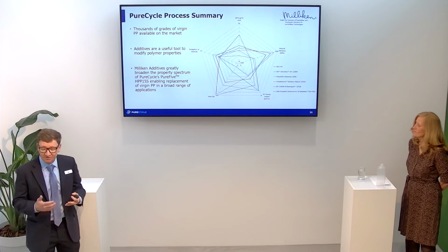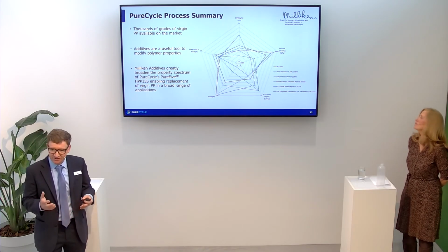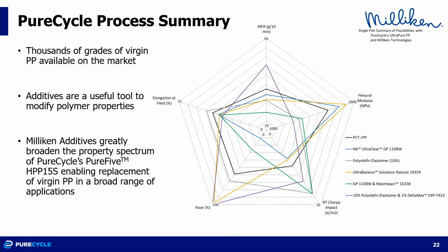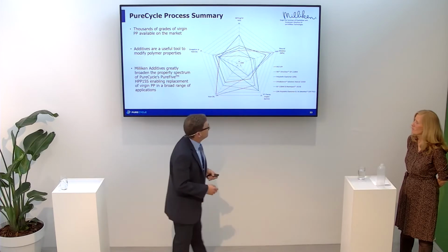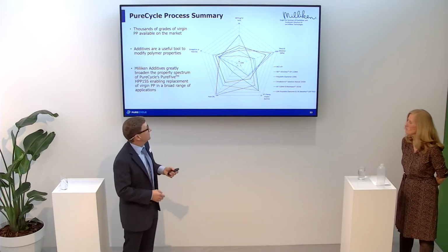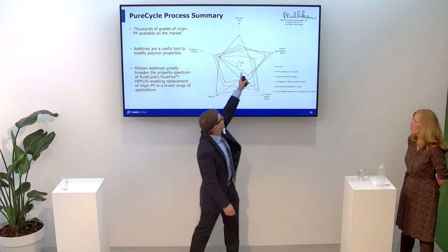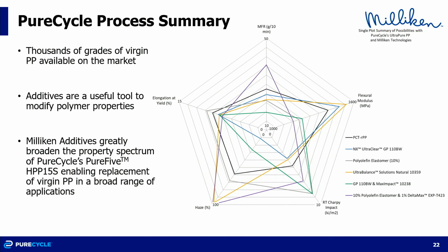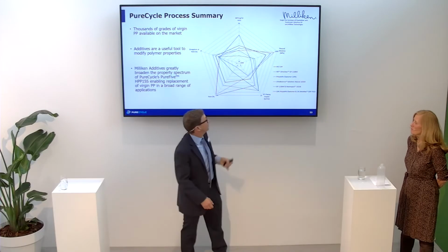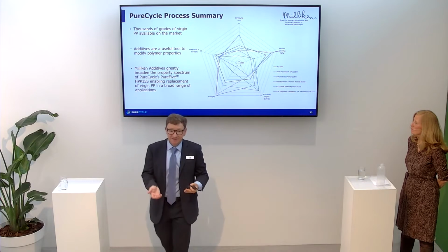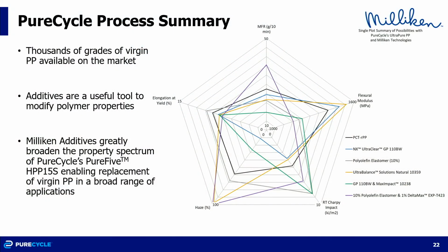So just to summarize where we've been, it's a really busy chart, but I think it's a good demonstration of how we push the boundaries of a single material to meet multiple different packaging applications. The black curve here is the PureCycle material that's nucleated. When we add the NX8000, the clarifier, you can see that haze really decreases compared to where we start. Similarly with the max impact, haze is quite a bit better. If you need more processability, the Delta Max additive or some of our other Delta Flow masterbatches can give you the higher melt flow in this case.